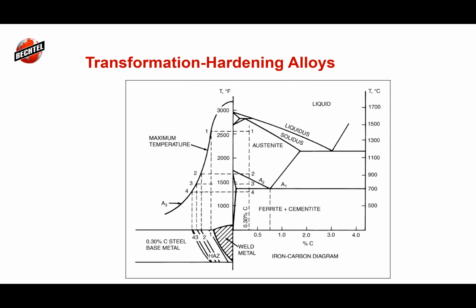If anybody has to do weld procedures, and everybody has different backgrounds, but I think API 1104 is pipeline. I think they have Charpies that you have to do at fusion line +2, fusion line +5. Some of the DNV and the offshore specs have to do that as well. And if anybody's wondered why we've had to do so many of the Charpies right at the fusion line, 1 millimeter off, 3 millimeters off, 5 millimeters off, it's for the exact reason of what we're looking at here when we look at the heat affected zone.